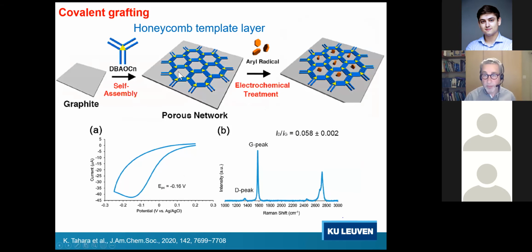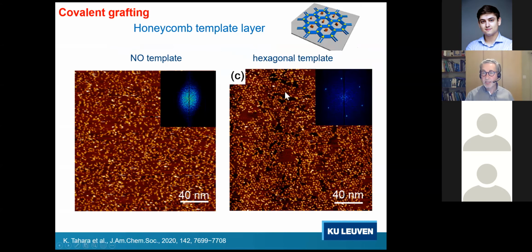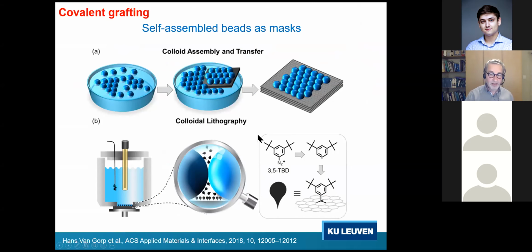Well, you can also use a porous network to introduce the same type of templating, where now the radicals are expected only to attack the graphite surface in the porous areas. And here you see indeed what we could realize recently. You see it nicely here at the right-hand side, where we have a hexagonal template as shown in this cartoon. By the appearance of the bright dots, and each of these bright dots is such a grafted molecule, it really nicely reflects the honeycomb-type lattice formed by the molecular template. So this is control at the nanoscale.